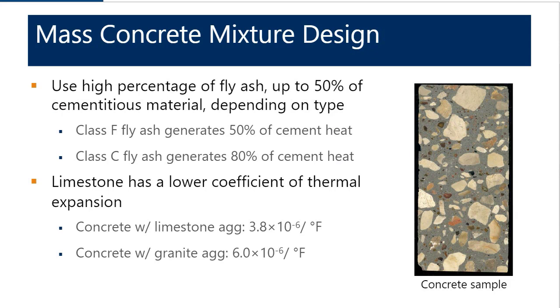So as we've talked about, the concrete mixture design, the total cementitious materials, have a very large impact on the total amount of heat that's generated. There are ways that we can reduce some of the heat that's generated by a concrete mixture. And one of the most effective ways that we can do that is by using a high percentage of fly ash, up to 50% depending on the type of fly ash that you use. Class F fly ash is a particularly efficient material for reducing heat generation in concrete.